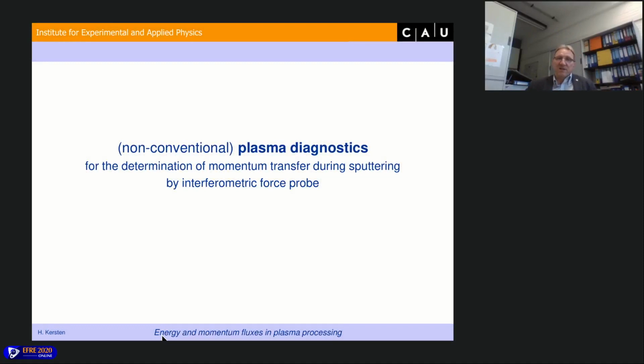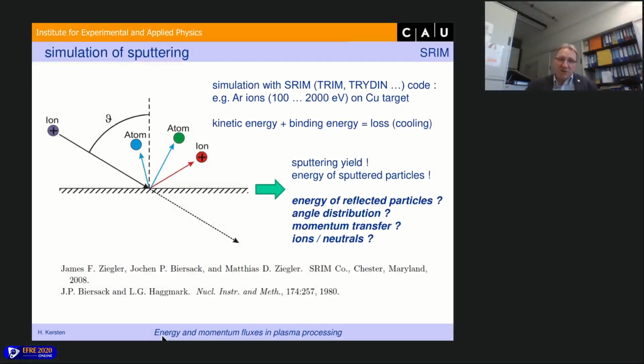I explained the energy flux measurements, and now I explain the measurement of the momentum transfer. The idea is simple. If you have sputtering, for instance, this is the target, there is an incoming ion for sputtering, and there might be a sputtered atom or another sputtered atom, and there might also be reflected ions. That means you have an incoming momentum and an outgoing momentum. You can calculate or simulate these processes with simulation codes for sputtering, like SRIM or TRIM or TRYDIN.